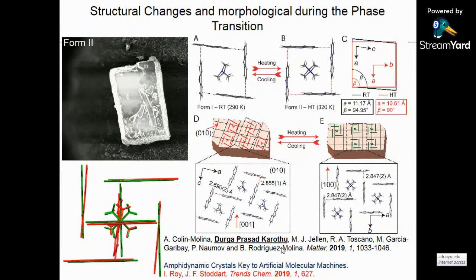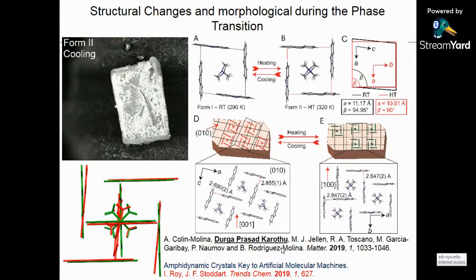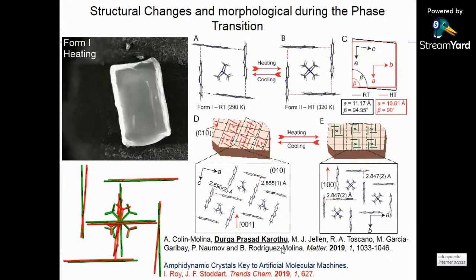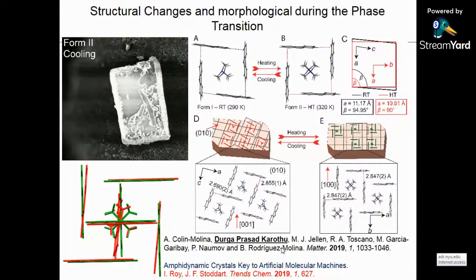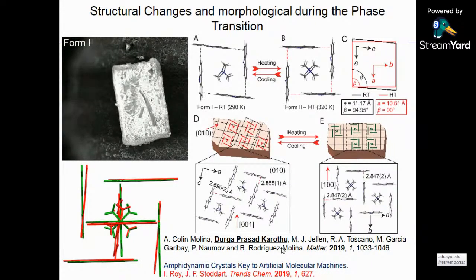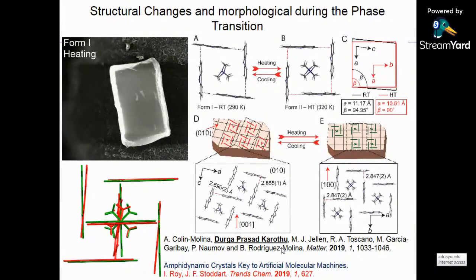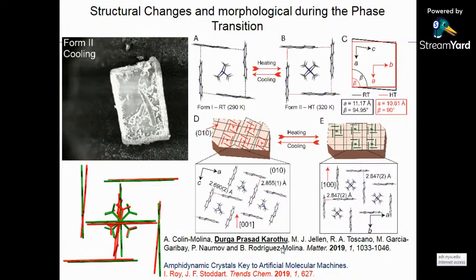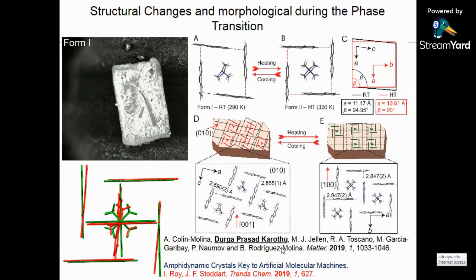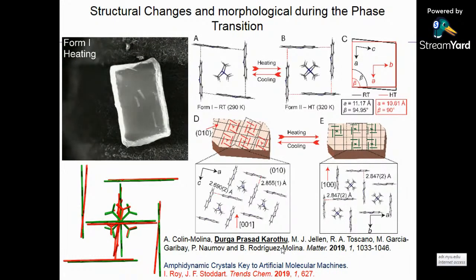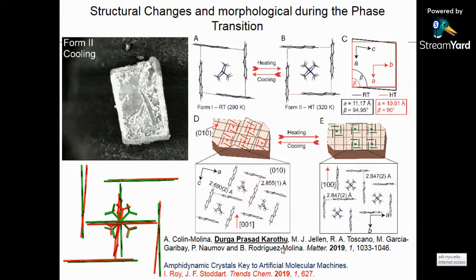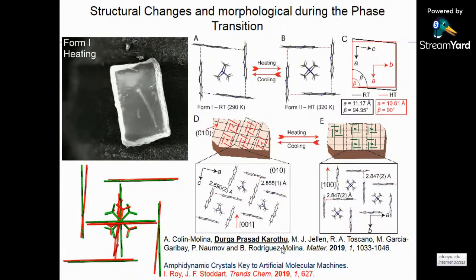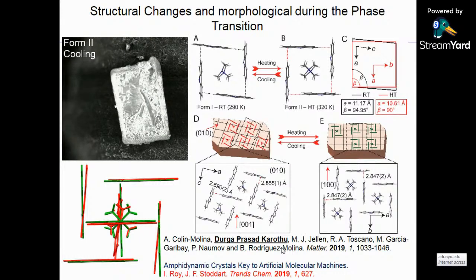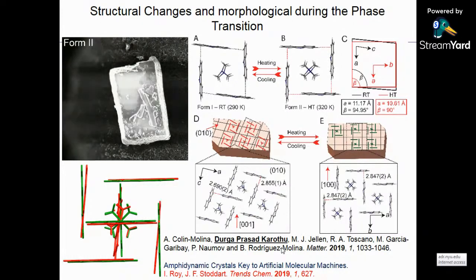On the left side, you can see here, this is the superimposed structures of both polymorphs at room temperature and high temperature. This is the only change between both forms. See, the red form is the room temperature form, green form is the high temperature form. That means this distorted square structure becomes an exactly perfect square shaped structure. This is the only difference between these two forms. Because of this change, the crystal is actually able to show translational, rotational, and upward motion.